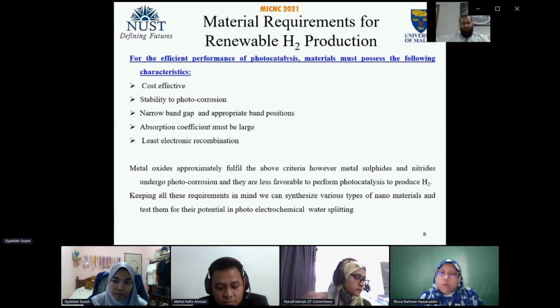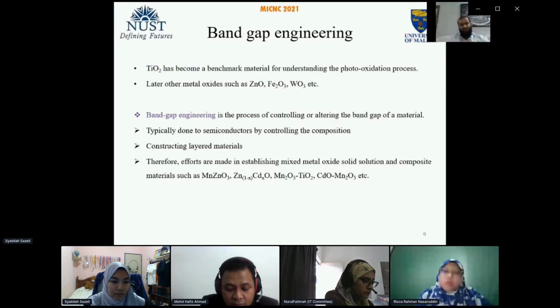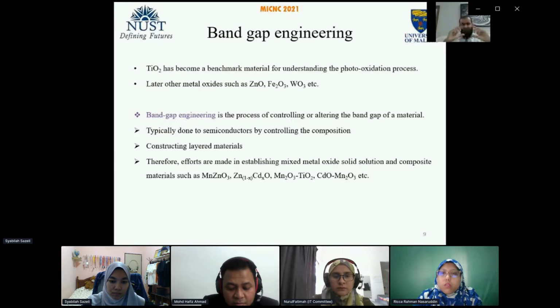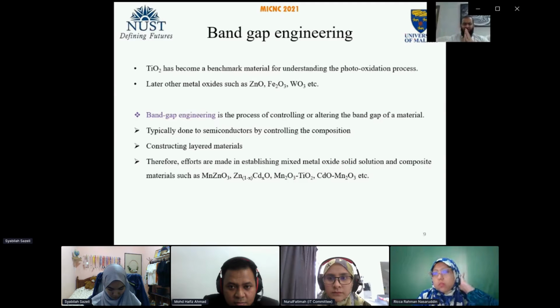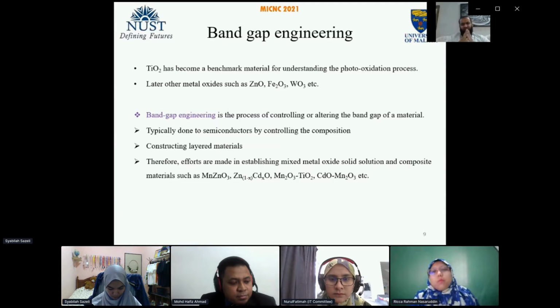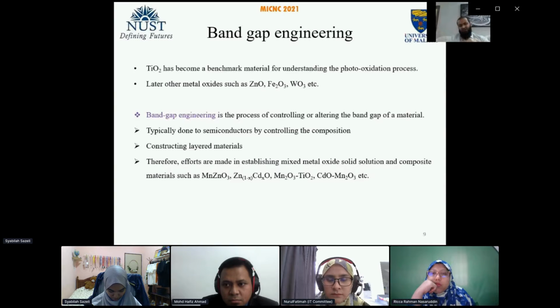Keeping these in mind, several materials have been prepared previously, in which titanium oxide was the first material studied by Fujishima. However, it was a photoactive material, but the band gap is very high. It works in the ultraviolet range of radiation. There are also zinc oxide, iron oxide, and tungsten oxides that have been studied. But the problem is that these materials either have a high band gap, or they have a low band gap but their stability is not good. They may undergo photocorrosion.